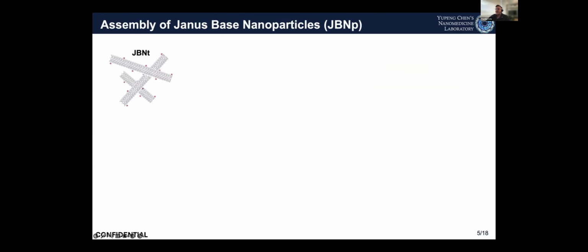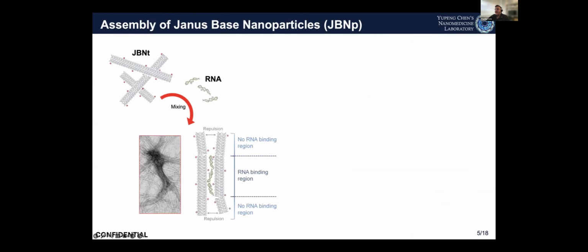Our Janus-based nanoparticles are fabricated from the same starting materials as all Janus-based nanomaterials, called Janus-based nanotubes. Here, JBNT and RNA are mixed together by simple pipetting to form a JBNT and RNA complex where the charge-charge interactions between the negatively charged RNA and the positively charged nanotubes create RNA binding regions, and the repulsion between the nanotubes leaves non-RNA binding regions.